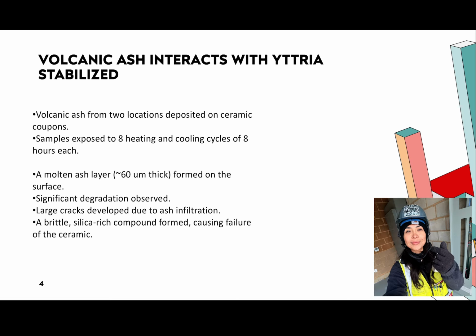This paper investigates the crucial issue of material degradation in high temperature environments, specifically focusing on the interaction between volcanic ash and the ceramic coating used in critical applications like jet engines. The primary goal was to evaluate the durability of yttria stabilized zirconia, the 7YSZ ceramic material, when it's exposed to the Popocatépetl volcanic ash at the extreme temperature of 1350 degrees Celsius, which would be mimicking a real world engine